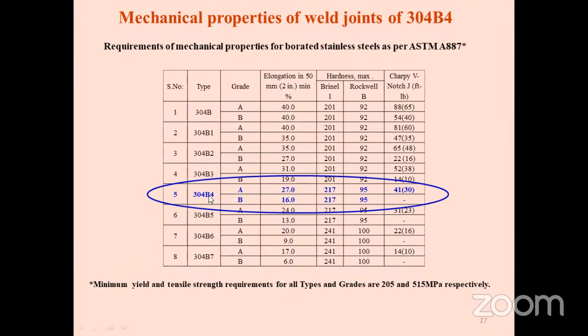So now coming to the mechanical properties of this borated stainless steel given by ASTM standards, we can see that borated stainless steel 304B4, which is used for our PFBR, has certain requirements for elongation, hardness, and impact toughness value. But in this case, we can see that there are two grades of stainless steel, grade A and grade B. Whatever we have used for our PFBR is grade B material.